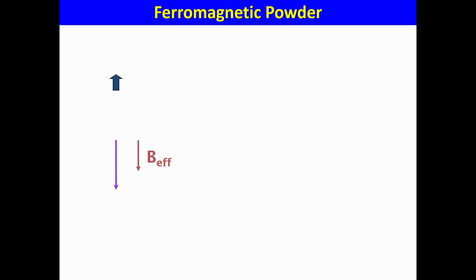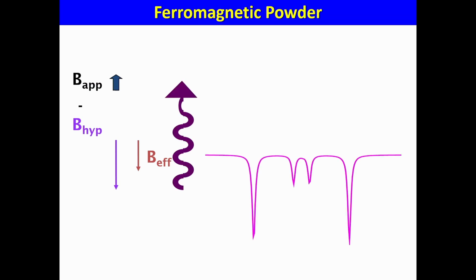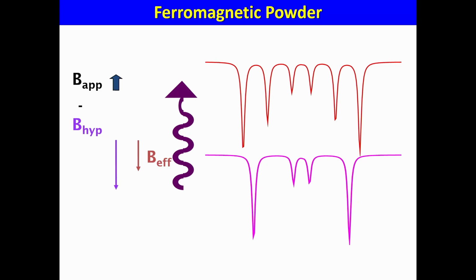So now you have to know what about the hyperfine field. In such a case, it is opposite to the magnetic moment. And what you will see is that you have to subtract the value of the applied field. And finally, in the case of an external field parallel to the gamma beam, you will obtain this. That means a decrease of the distance between the external lines, and you also have a disappearance of such lines, as we discussed before, according to the orientation of the magnetic moment with respect to the gamma beam. So, by such a way, you can conclude, from the 3, 0, 1, that your hyperfine field is anti-parallel to the magnetic moment.